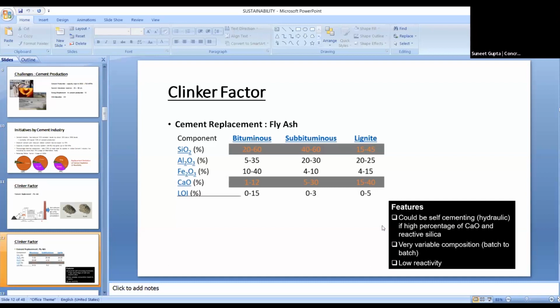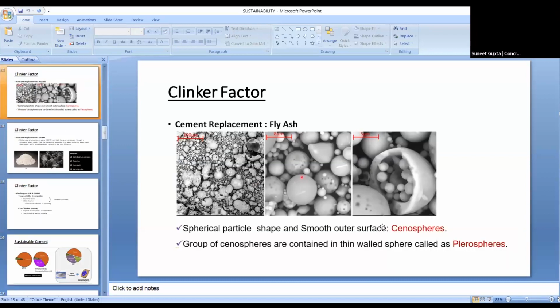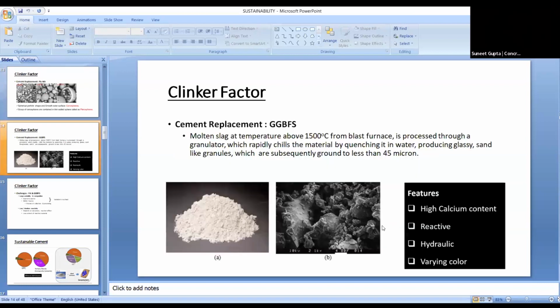So we try to use this coal as far as possible, but where we cannot, we use other coal, and we try to redefine our manufacturing or quality process through these fly ashes also, keeping the cement quality the same. This is the kind of fly ash we use. You can see how small the particles are, in an SEM magnification up to 2000 times.